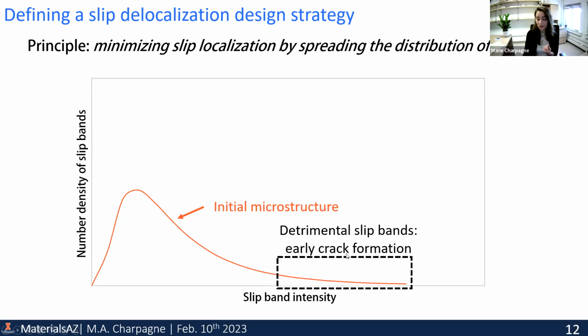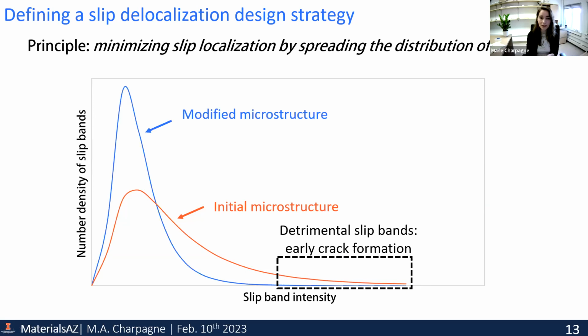Now that we know where they are, how can we engineer materials that have a modified microstructure, so that we get rid of these detrimental slip bands and favor the formation of smaller slip bands of reduced intensity, and have more of these smaller slip bands? Of course, we cannot have a distribution where we just cut off the tail of the orange one, because we have a given amount of plastic deformation that the material is subject to, right? So this is a fixed parameter. Imagine the area under that curve needs to be constant, but we can actually try and shift the curve to the left here so that we don't have those very intense slip bands anymore. So that's our approach.